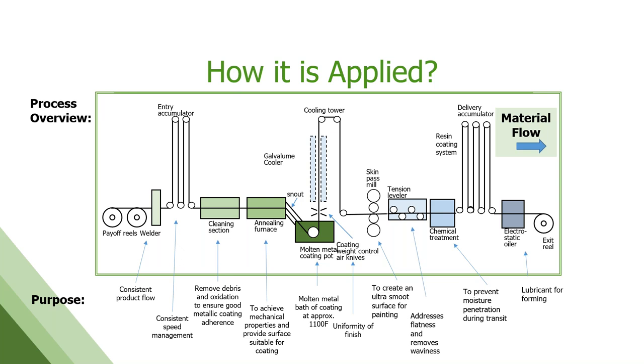Then goes through a skin pass mill if it's going to be painted, or a skin conditioning mill. That really gives you an extra smooth surface for painted product. Then it goes through a tension leveler, which corrects any shape, so we have a nice flat product. And then at the exit end of these lines, if it's going to be bare product and not get painted, you might put some chemical treatment on it to help prevent corrosion, or a clear resin product, which prevents fingerprinting on the strip and also aids in roll forming if it's not going to be painted. And then the coil is wound up and off it goes to its next process.